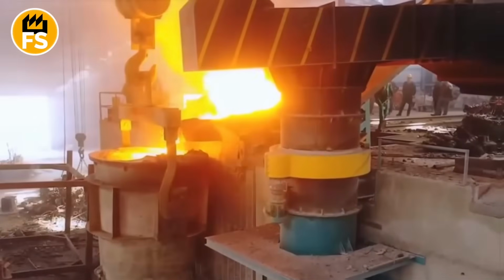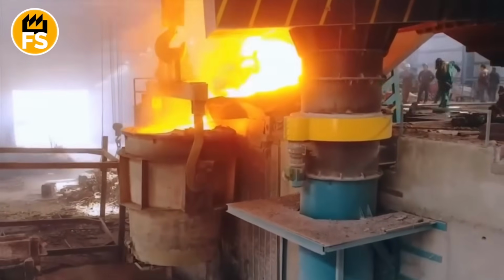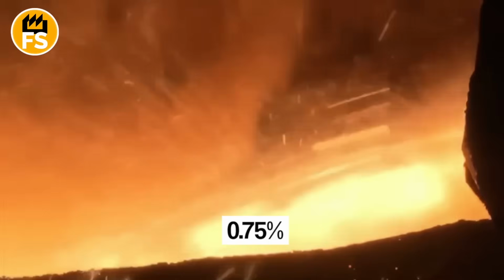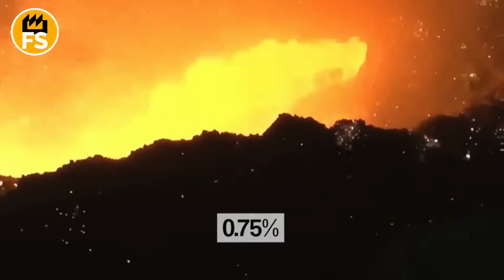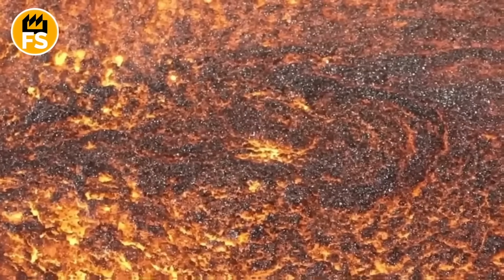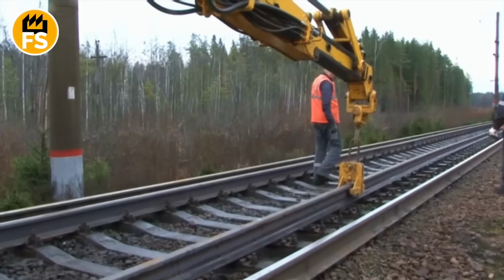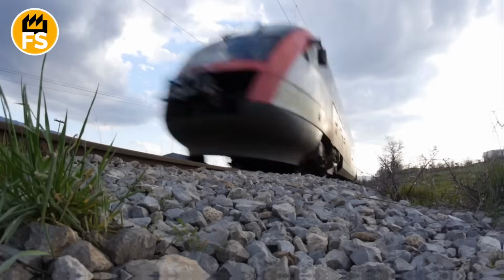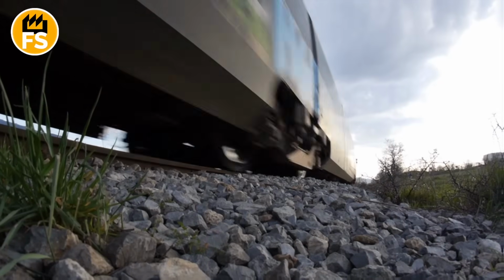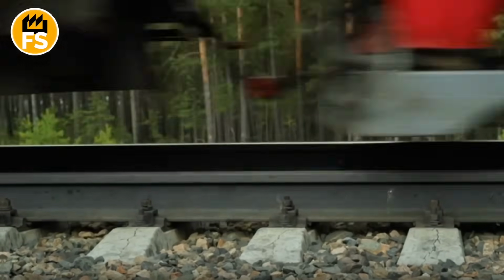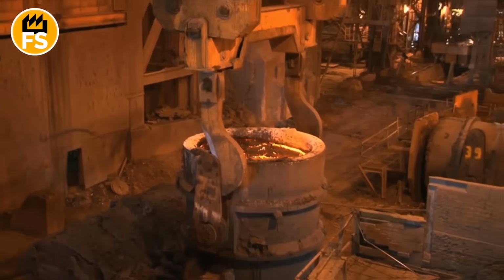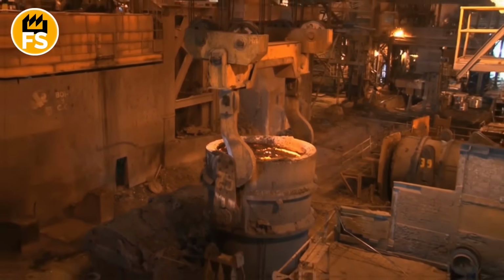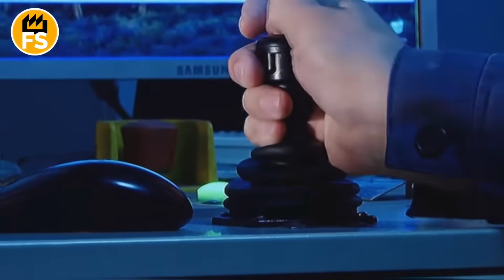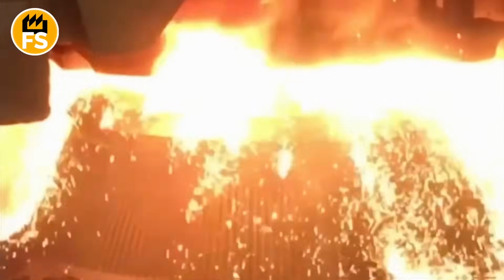And what comes out at the end is steel with a carbon content of precisely 0.75%. That specific number is absolutely critical, because if there's too much carbon, the rail becomes brittle and will shatter when a train wheel hits it. But if there's too little carbon, the rail wears down way too fast, and you'd have to replace it every few months instead of every 40 years. The margin for error here is incredibly thin, like thinner than a human hair, because one small mistake at this stage ruins 300 tons of steel that has to be melted down and started over.